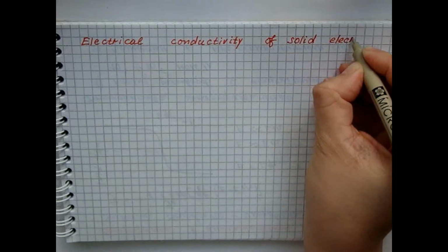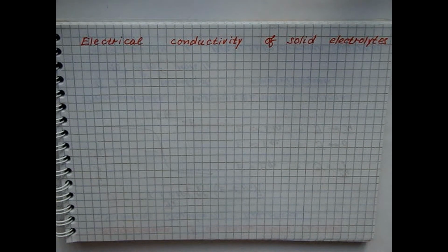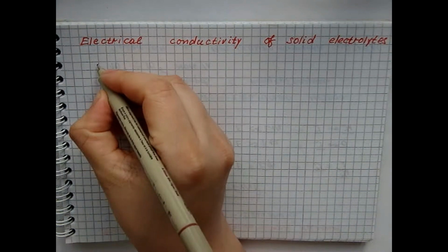For the first time, the conductivity of solid electrolytes was investigated in detail by Tubandt, using a method similar to the Hittorf method for electrolyte solutions. As an example, we can consider the experiments with the alpha modification of silver iodide. Tubandt pressed 3 cylindrical tablets from silver iodide, weighed them, and clamped them between a silver anode and a platinum cathode with a known mass.